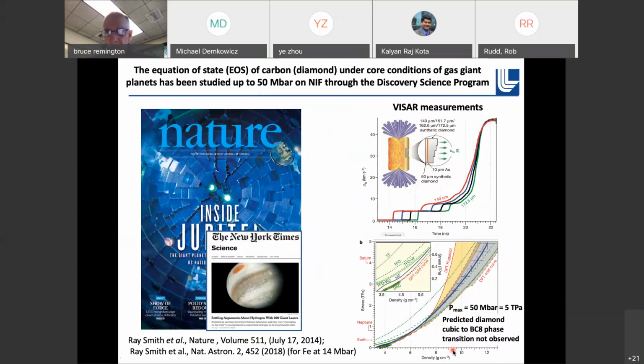And then with a sophisticated analysis, you can produce this figure on the bottom right, which is a plot of stress versus density. The experimental results are the thick blue curve and the data points along it give the error bars. What's interesting to note is the comparison to density functional theory. Density functional theory for the Hugoniot is the upper red curve. So clearly we are achieving higher densities at the same pressure, or the same stress, for the experiment, because it's a ramp compression, not a shock.